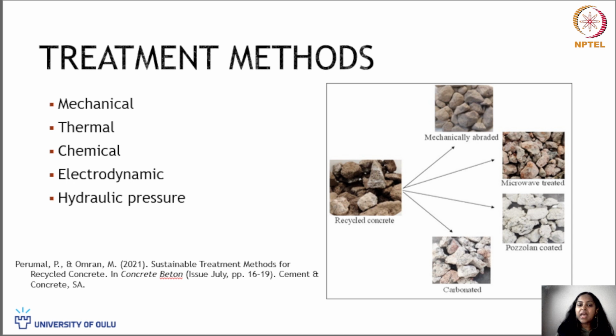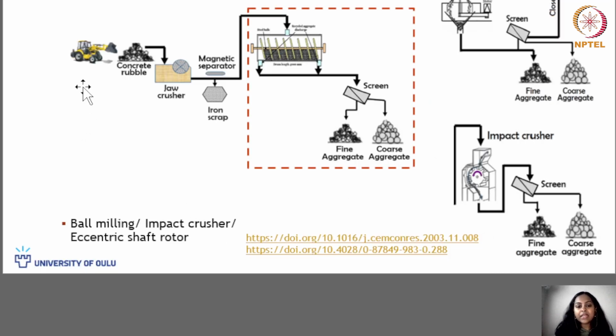And there is chemical treatment, where you use acids to remove this old mortar layer. There are also some technologies in recent days like electrodynamic methods and hydraulic pressure using water. Those are applied to remove the old mortar from the surfaces of the aggregate. Here is one example, which is a mechanical treatment, wherein you can see the concrete rubble goes to the jaw crusher, where it is crushed into small pieces of aggregates, and then there is a magnetic separator to separate the iron scraps that could be in the demolition waste, and then it goes to the mechanical scrubbing action, which is a mechanical treatment to remove the old mortar, and then goes to the screen where it can be separated into finer and coarser fractions. This is a typical processing method for recycling concrete to produce aggregates.